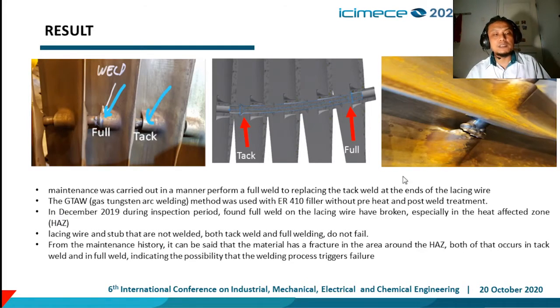In December 2019, during the inspection period, the full weld on the lacing wire was found broken, especially in the heat affected zone. You can see here. Lacing wire and stub that are not welded, both tack weld and full weld, do not fail and never fail. From the maintenance history, it can be said that the material has a fracture in the area around the heat affected zone, both in tack weld and full weld, indicating the possibility that the welding process triggered failure.